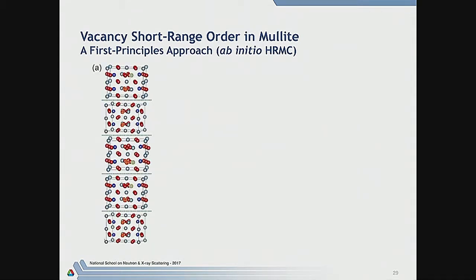Ironically, a quicker way of doing it nowadays probably is to use ab initio methods, which is to actually use density functional theory to calculate what the vacancy distribution should be. So in this case, we have a whole series of supercells. These are just a small subset of unit cells in the crystal, and we put in vacancies in random configurations within these supercells, and then somebody like Peter Zapol at Argonne did a total energy calculation for each of those supercells. What is the energy of the whole supercell in absolute terms, given this vacancy configuration.